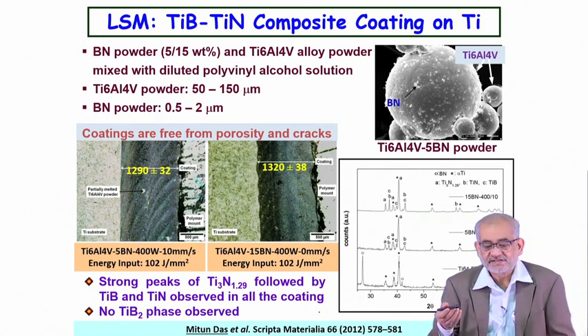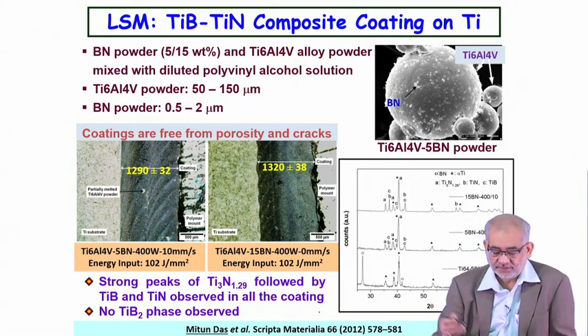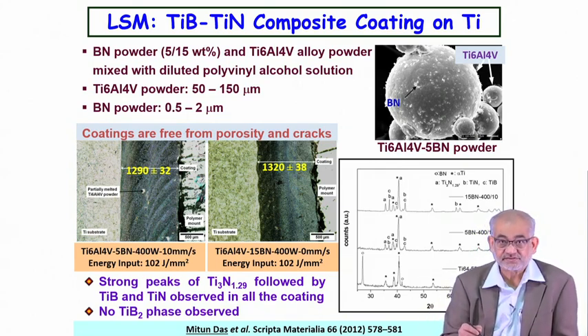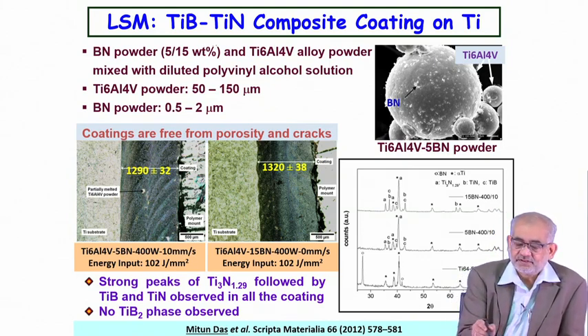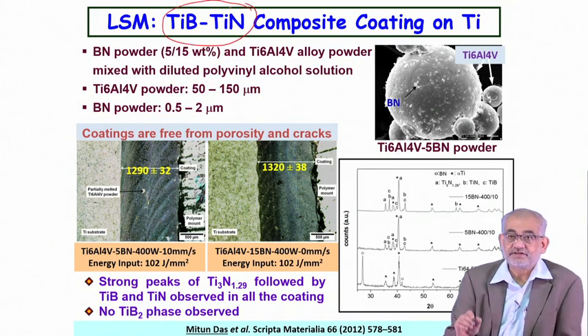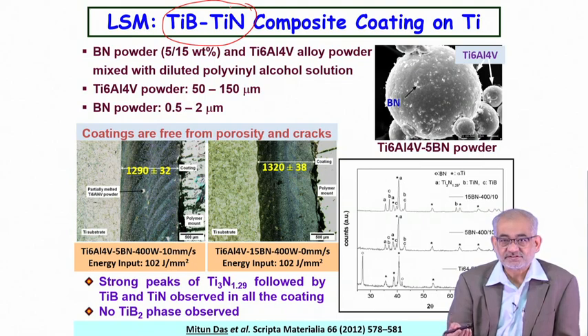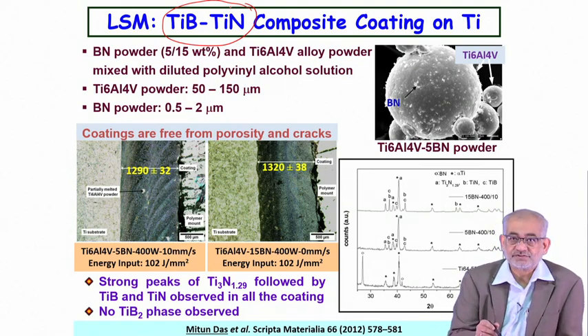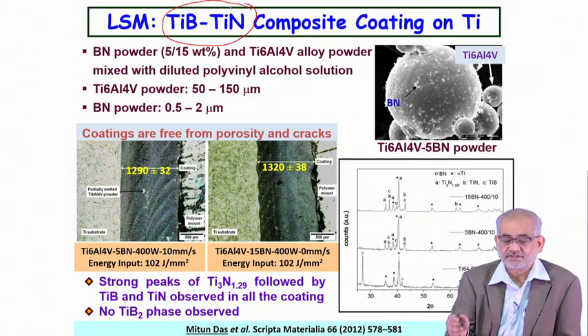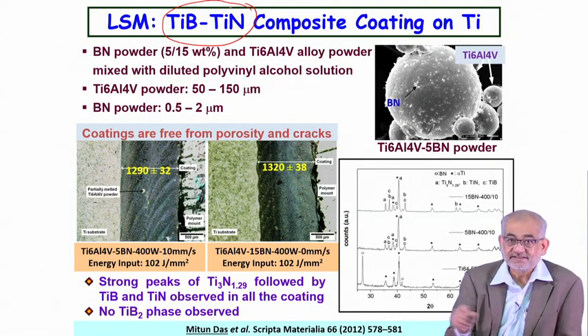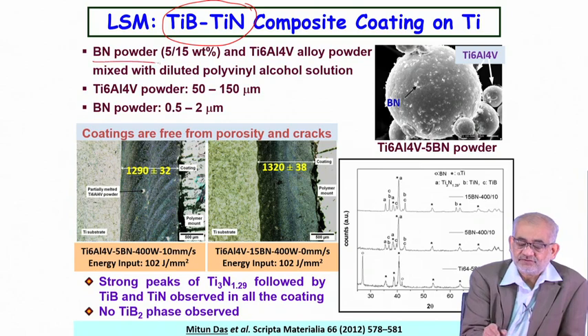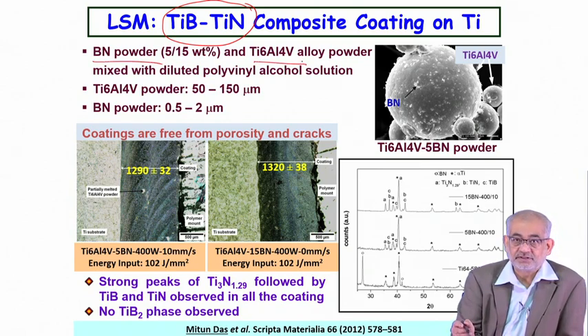I want to just show you an example from certain research output from our own group. This is picked from the PhD thesis of Mitun Das, who is a scientist in a CSIR laboratory. Say, for example, you want a composite coating of boride and nitride together. Now, there's no single pure synthesis process which will give you such a complex combination of a boride and a nitride both on top of a surface. So using a laser-based technique, you actually can create it. You start with boron nitride powder and titanium alloy powder and mix them. You pick the powders in different sizes, mix them well, spread them onto the surface, carry out laser surface melting, and in the process you can produce layered structures with very high, extremely high hardness.